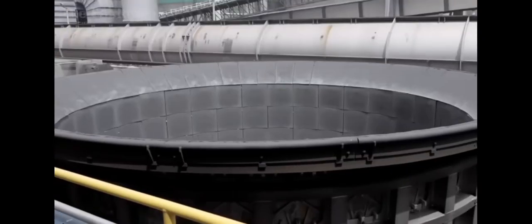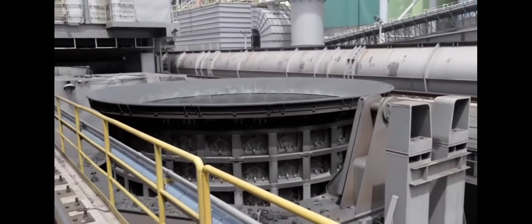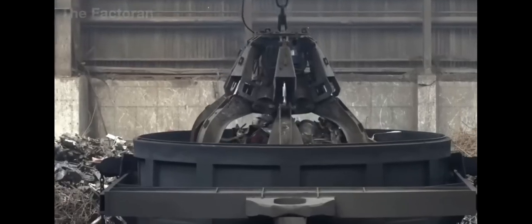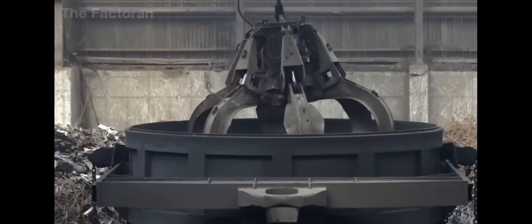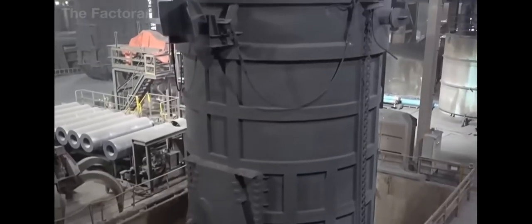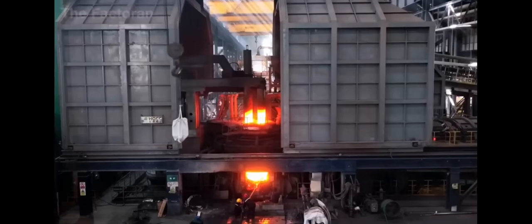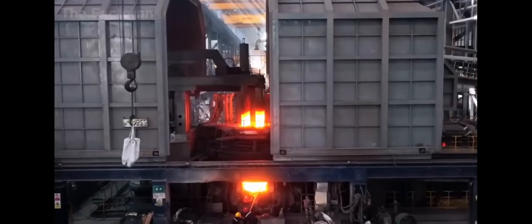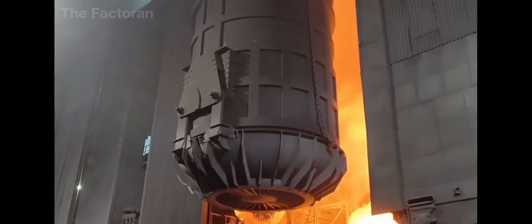Cranes lift individual batches of steel scrap and release them into the electric arc furnace. Once the furnace is closed, the electrodes are lowered close to the surface of the metal and begin delivering a high-intensity electric current, generating an arc with extremely high thermal energy. Temperatures can reach up to 3,600 degrees Fahrenheit, allowing the steel to heat rapidly.